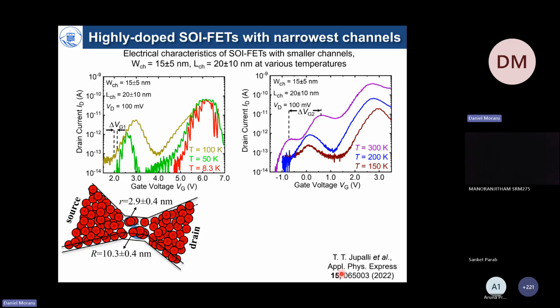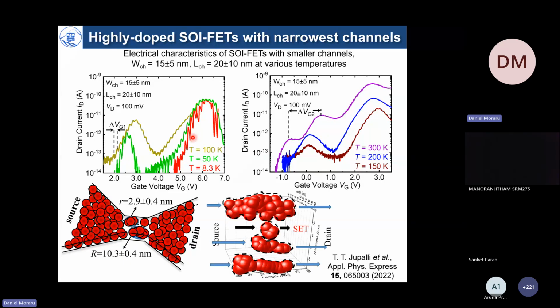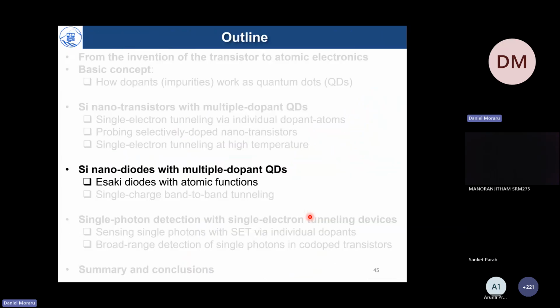As reported in this Applied Physics Express paper by my PhD student, the analysis leads to the fact that we are dealing with two quantum dots in the channel. One is a little bit smaller, one is a little bit larger. The sizes can be calculated from the periodicity between these peaks. In a way, we were able to observe SET through these two different quantum dots, but suppressing, cutting off these metallic paths between source and drain because we squeezed down the dimensionality of the channel. So this is room temperature operation of SETs, and this is what I wanted to leave you with about this part of my talk.